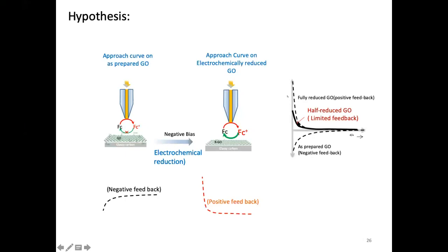But once we reduce it, you know that we reduce chemically sometimes with sodium borohydride or hydrazine. Okay, you remember this? So graphene oxide, and we form reduced graphene oxide. But you can do the same thing with electrochemistry. We can apply negative bias and reduce this graphene oxide into reduced graphene oxide. But how am I going to measure this change in conductivity in situ?